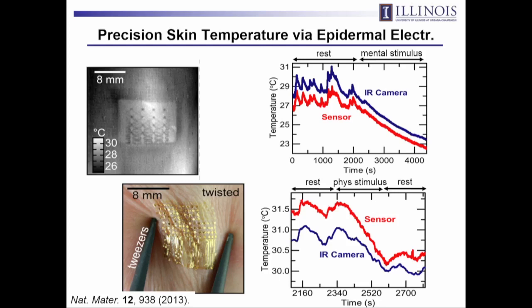We can quantitatively compare that data to those that we capture with this epidermal electronics, essentially exactly the same. But we don't have the motion artifacts, and it's in a wearable format as opposed to something that's only relevant in a laboratory setting. So these curves are actually offset for the purposes of comparison. But you can see these natural oscillations, these very fine temperature variations. That's just associated with natural patterns of vasoconstriction and dilation. And so the amplitudes and the frequencies tell you something about cardiovascular health.